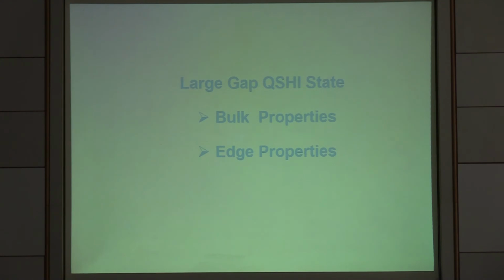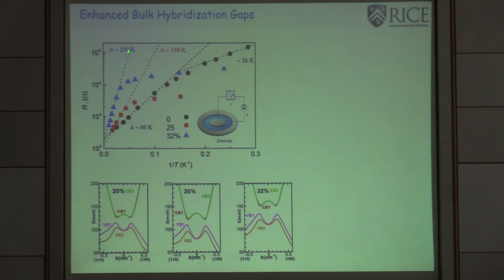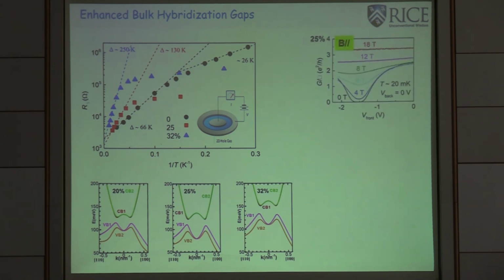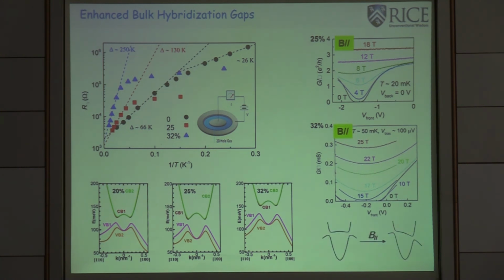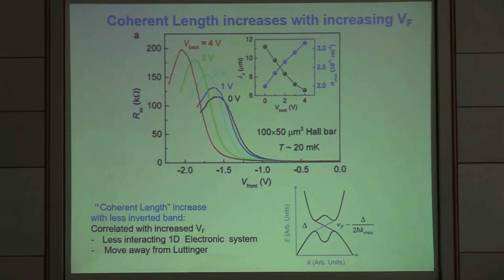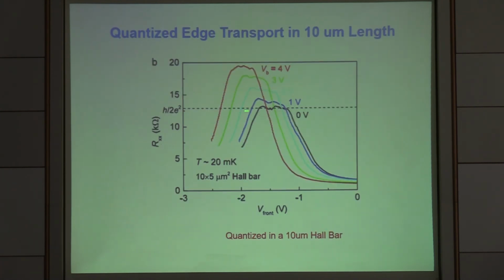Now we are going to just flash some of the results. First is indeed the energy gap. In this case, for 32%, we can measure 250K instead of the previous 66K. Then another thing related to this: the interaction between the edges now became weaker. Therefore, we find the characteristic length actually enhanced to more than 10 micron. In this case, we can have a characteristic length as high as 11 micron. One can tune this by changing the Fermi velocity through changing the density, and you can get a range from 7 to 11, just in one sample. And one can find a quantized plateau in a sample which has a relatively long size, 10 micron.